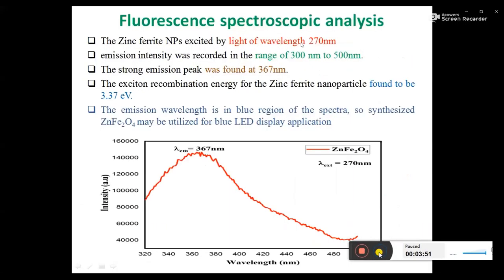Fluorescence spectroscopy analysis. The strong emission peak was found at 367 nanometer, which is in the blue region. And also we have calculated the exciton recombination energy of value 3.37 electron volt. So the emission is in the blue region. So zinc ferrite nanoparticle may be utilized for blue LED display applications.